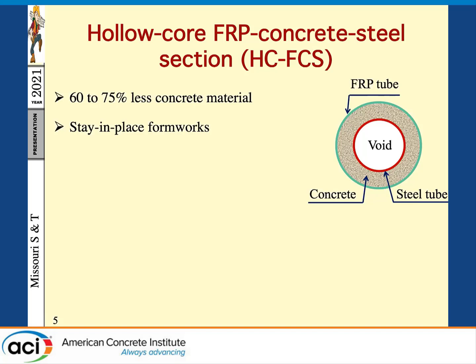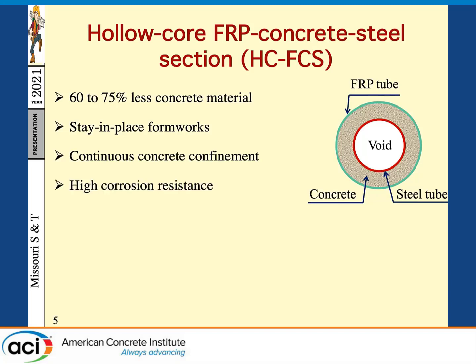We have two pipes, the inner steel pipe and the outer FRP tube, that act as stay-in-place formwork, so we don't have formwork, which can significantly cut construction time. We have excellent concrete confinement. Concrete cannot escape, cannot go anywhere, because from inside you have the steel pipe, from outside you have the FRP tube. It's as if you use a spiral, but with a pitch of 0. It's continuous. So we have excellent confinement. We move the steel pipe to the inside of the column, so it's protected under different barriers. You have the FRP outside, then 4 to 5 inches of concrete, and then your steel pipe. So it's well protected from the outside environment. Those are the advantages.